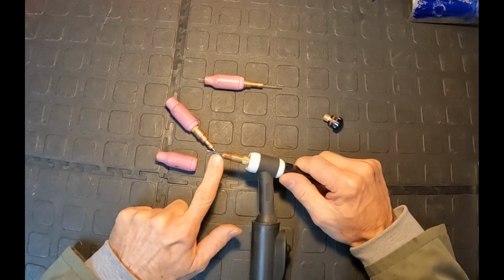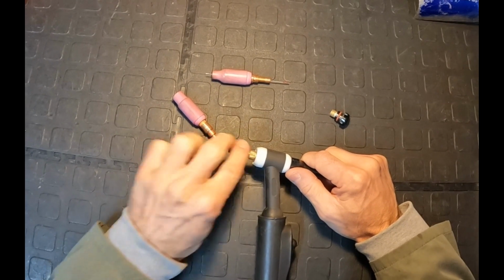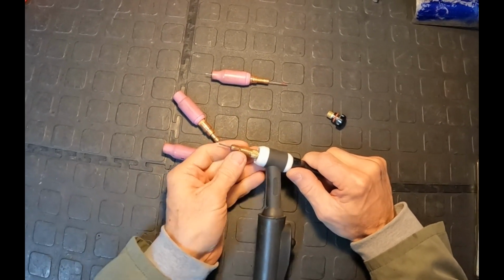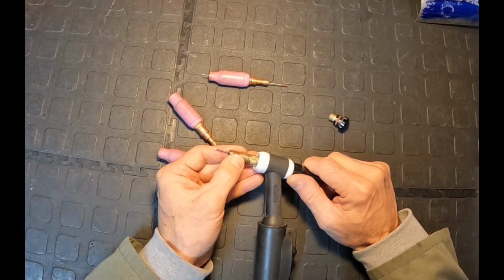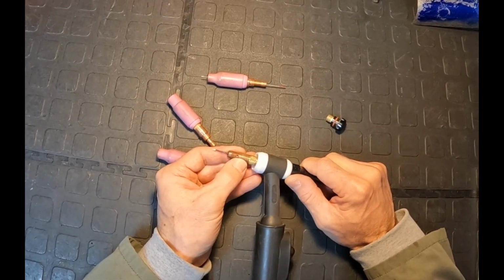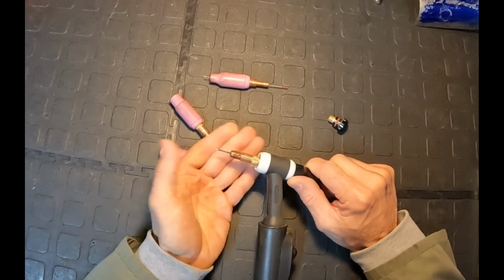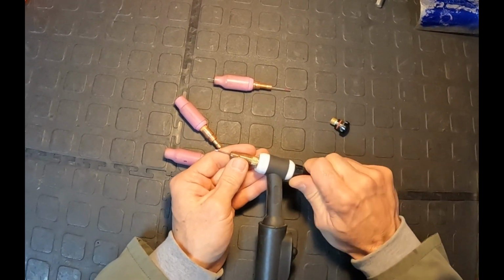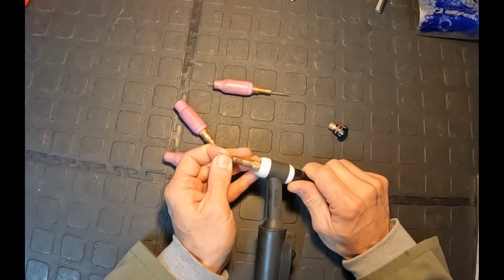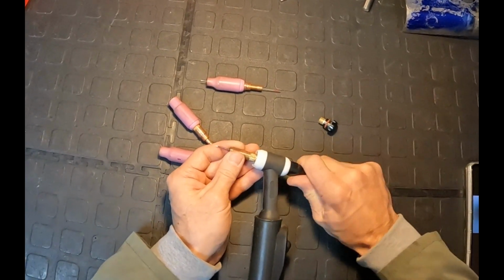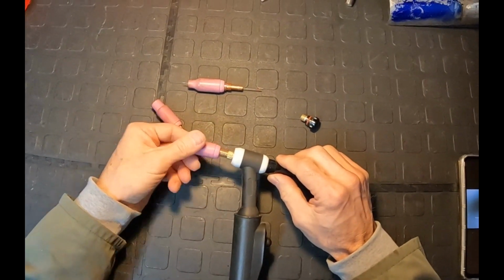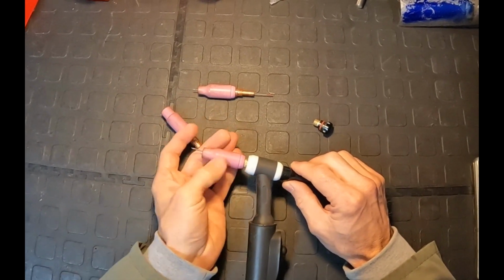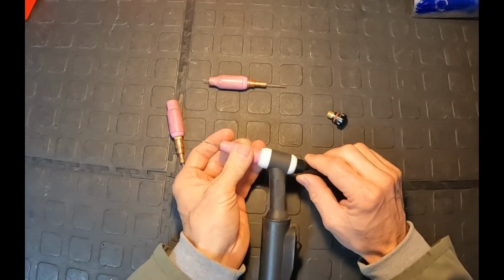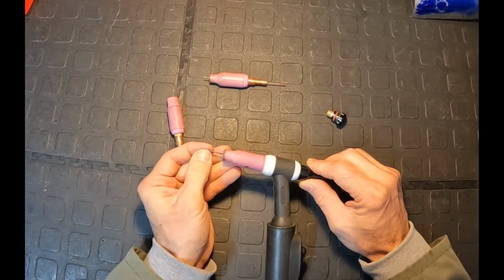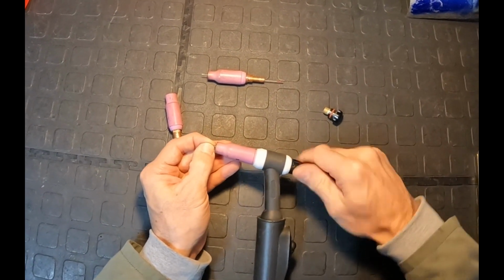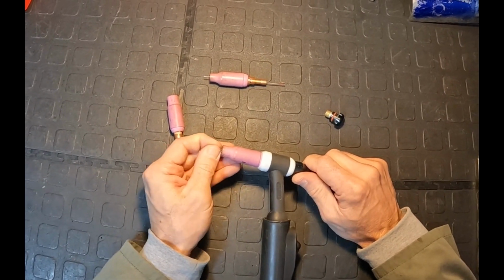It is very important then that this tungsten rod on the inside of the collet is very tight, because at the end of the day, this is an electrical connection. So if it doesn't make a good connection, then this tends to run hot, very hot in fact, and you end up damaging your torch. So you do need to have a good connection between the tungsten rod and the copper. Then it is just your gas shield that gets turned in to finish the torch, like so. Then that is tightened perfectly.